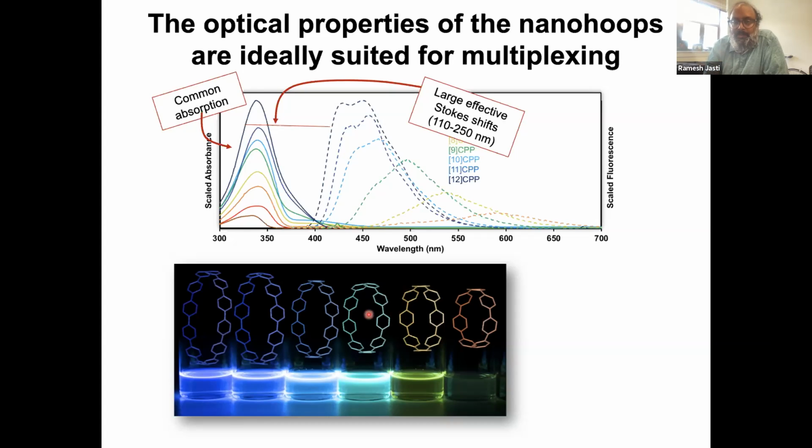Still relatively bright, but there's a trend there. And this is because as the structures get smaller and more rigid, that symmetry breaking event in the excited state doesn't happen. And therefore it's not allowed to fluoresce. And so you don't see any fluorescence. So it's kind of cool that because we can make these from the ground up, we can alter this, we